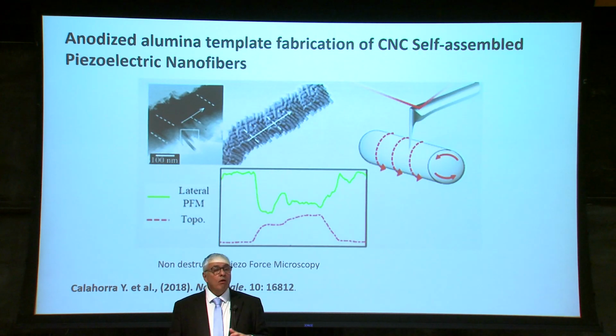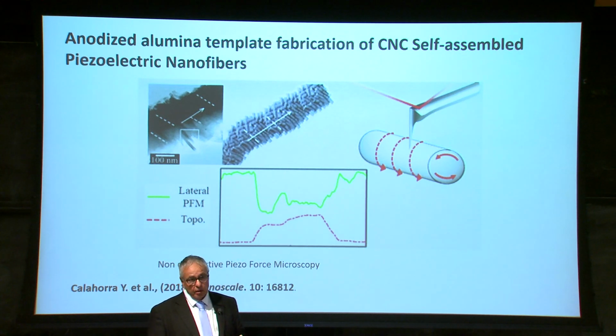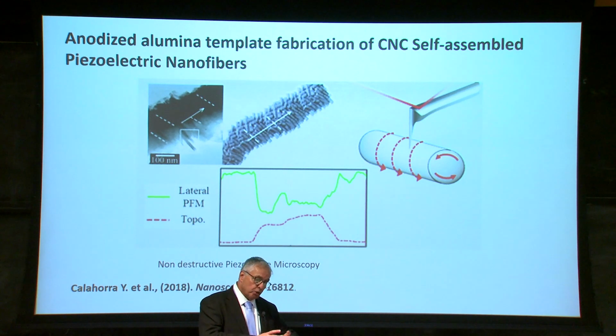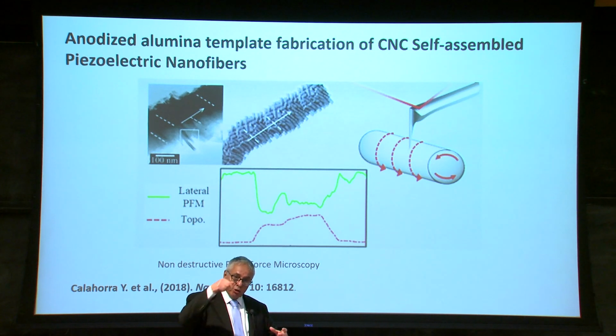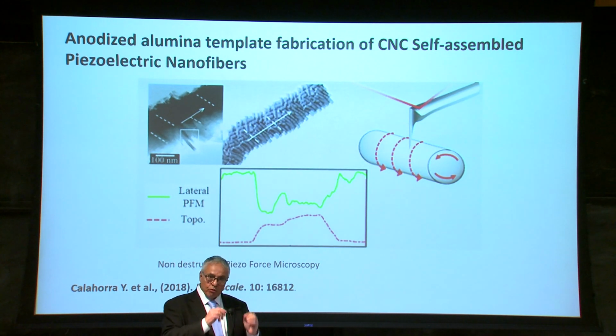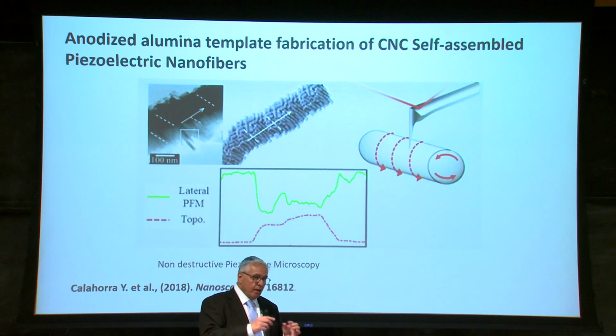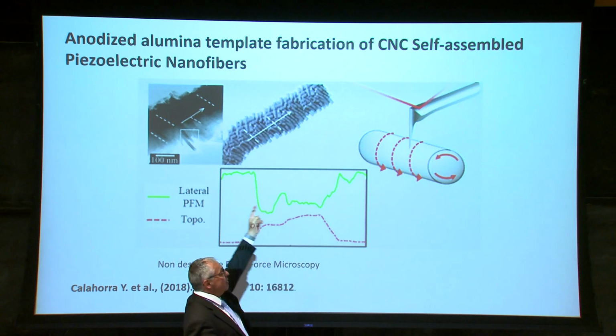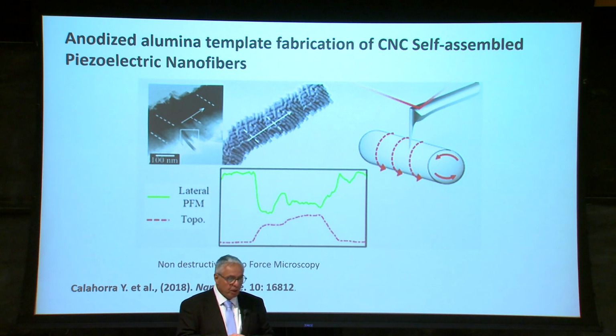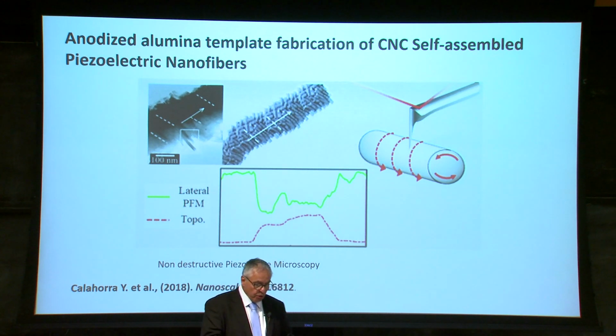Another very interesting feature of cellulose nanocrystals is the fact that they are piezoelectric. In this study, we took anodized alumina, introduced cellulose nanocrystals into the wells, and let them self-assemble as nanorods within the alumina. After that, we dissolved the alumina and produced these really long piezoelectric nanofibers. And when we measured them under a piezoelectric measurement device, which looks like a specialized AFM, we were able to measure the piezoelectric properties.